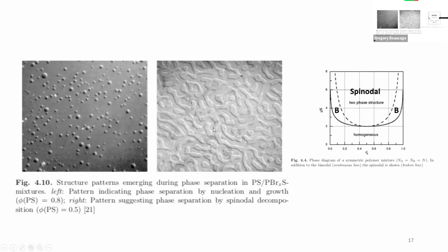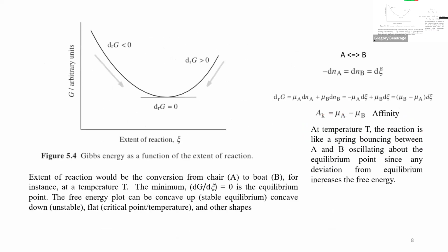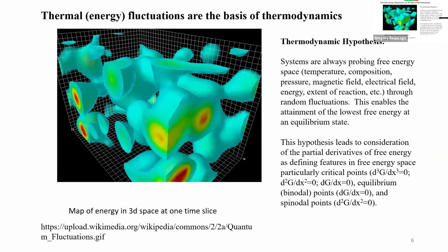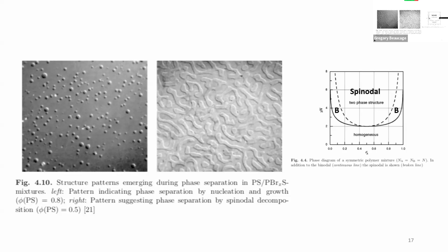And the speed of it is much slower because the dynamics of a polymer is much slower than metals. In metals it's milliseconds or picoseconds, in polymers it's seconds. So again, it's 100,000 times slower and 100,000 times bigger than in metals. This idea of fluctuations and spinodal decomposition was developed from metals, but the only place where you can really see it is in polymers. So metallurgy theories were adapted to polymers to predict these structures you can see.